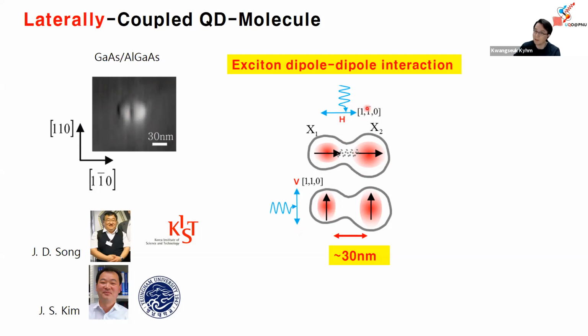But initially, we thought resonant excitation would be more efficient. Surprisingly, we found that even if non-resonant excitation is applied, for some reason the dipole alignments can be controlled through that non-resonant excitation. The exact mechanism is at the moment not clear, but we found there is some kind of interesting process.